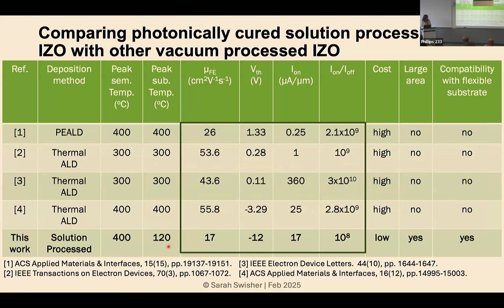In terms of the compatibility with large area substrates, spin coating is very easy. There are other ways you can do solution processing over large and flexible substrates as well. And the performance that we see is good. I would say it's not on par, right? It's not meeting the performance that we see with these ALD methods, but it's not terrible, right? And so when you have a requirement that says your substrate needs to stay much cooler, you're getting really, really nice performance for that type of application. Okay, so that's the curing part.